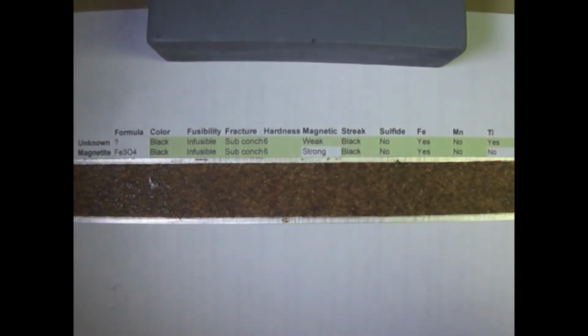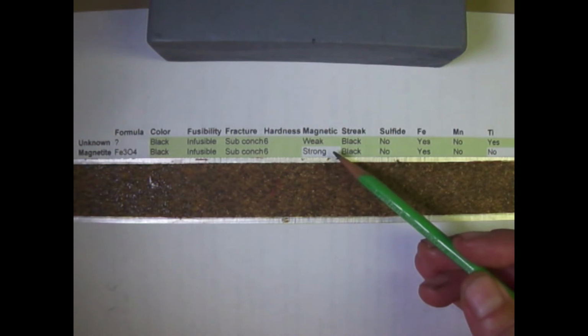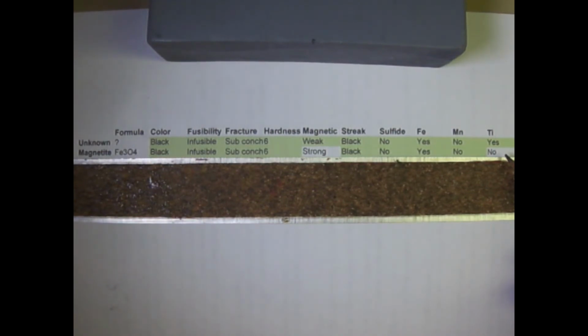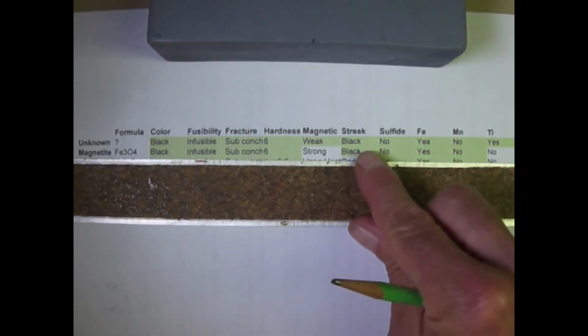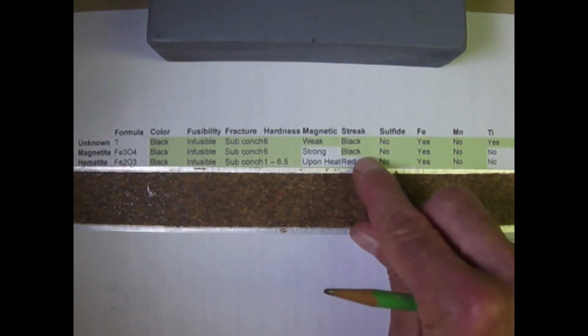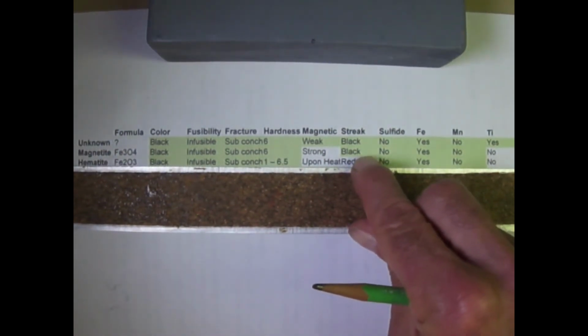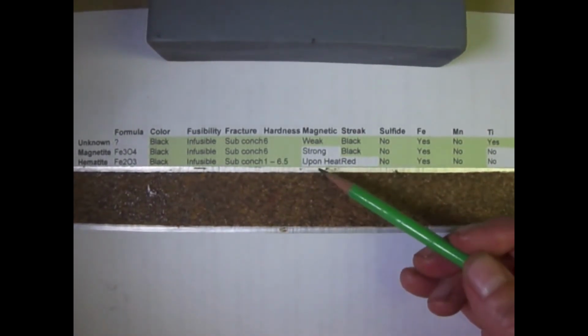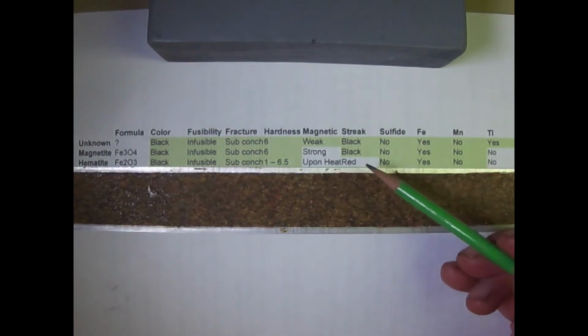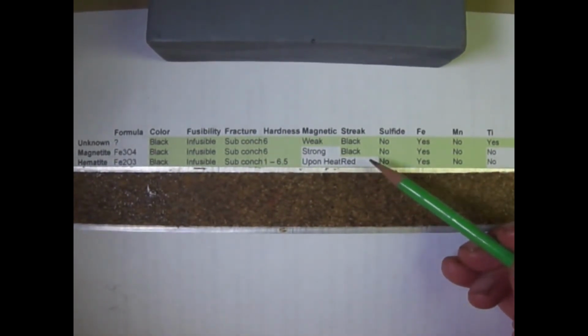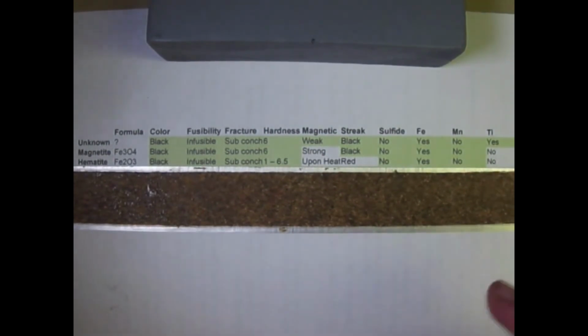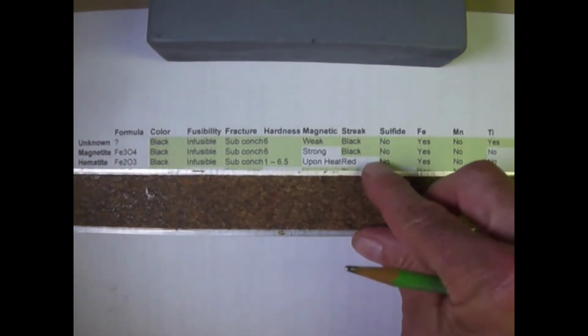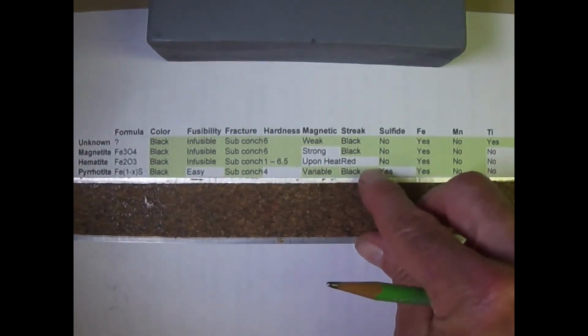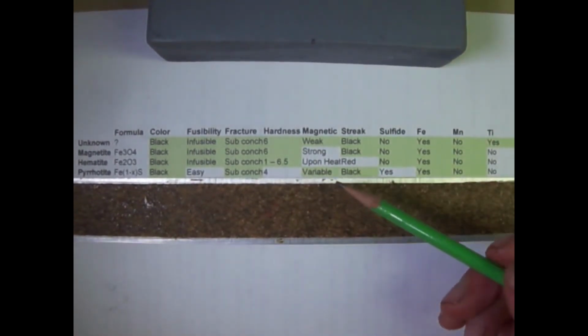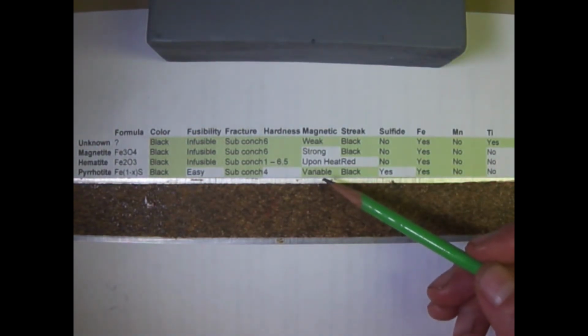So let's go to our possible candidates here on what this might be. The first one we were thinking was magnetite, and as we talked about, we knocked that off because it's not weakly magnetic, it's strongly magnetic, and it doesn't contain titanium. So that pretty well takes that out of contention. The next one was hematite, and as we just discussed before, it did not become strongly magnetic upon heating, nor did our sample have a red streak, and hematite doesn't contain titanium, so that further throws hematite out of the race.